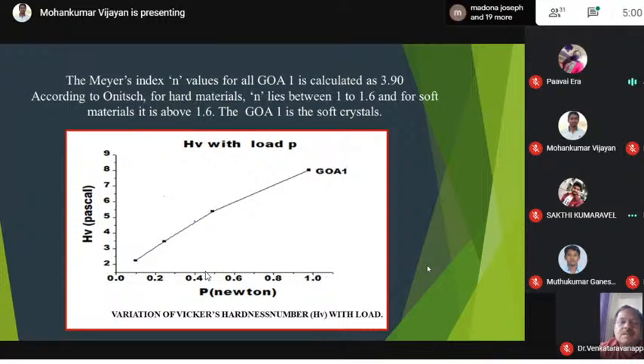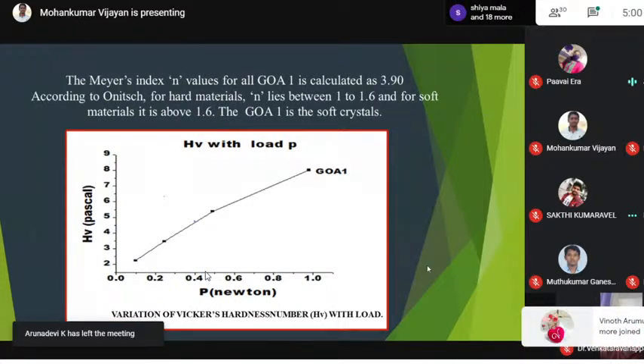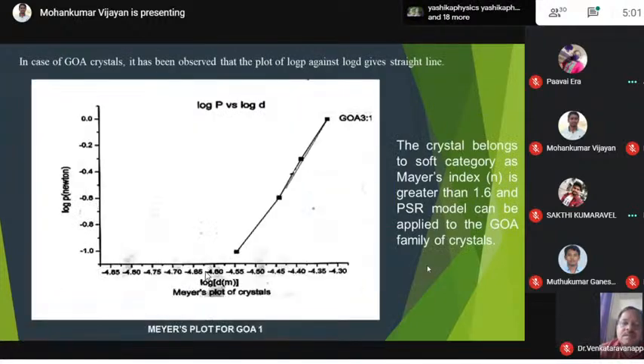And when the n value lies between 1 to 1.6, they are considered as hard. And in my case, it was 3.9. So it is a soft crystal. In the case of GOA crystal, it is observed that the plot of log P against log D gives a straight line graph. So the crystal belongs to the soft category as Meyer's index is greater than 1.6, and the PSR model can be applied to the GOA1 family of crystals.